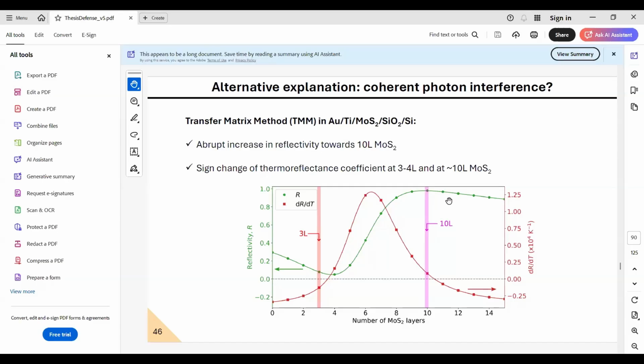Okay, I thought these were phonons as well. Sorry. Yes. Sorry, we put phonon and photon interference. It is difficult to distinguish quickly. But this is purely optical simulation, where first of all, we get the reflectivity from the first top surface due to the presence of all the interfaces underneath. And we use the temperature dependencies of these optical properties to retrieve the thermoreflectance coefficient, the estimated thermoreflectance. Got it. We also get a sign change, so from negative to positive to negative again. Okay, yeah, I thought this was a phonon interference simulation. So, but I missed the sign change, like you said. Okay.